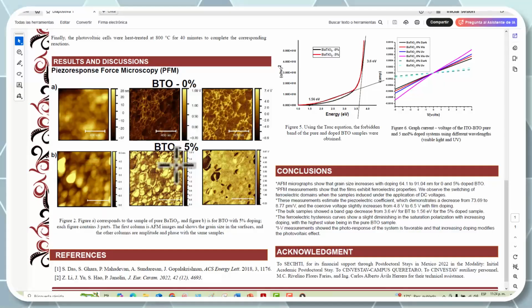The second and third columns present the amplitude and the phase micrographs. In the images in the second column, the amplitude shows the domain walls in the ferroelectric. In the phase images, we observe changes in the polarization direction as indicated by variation in contrast.